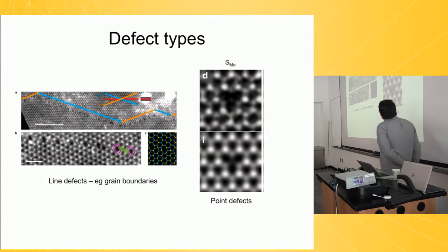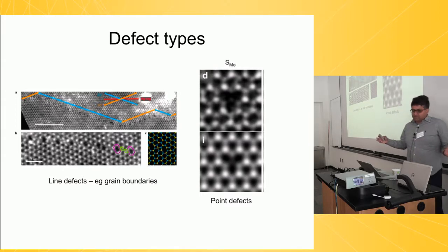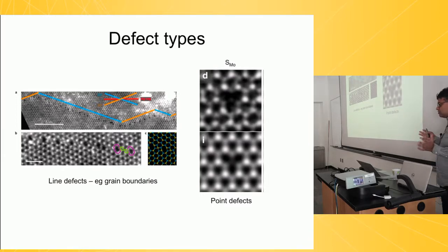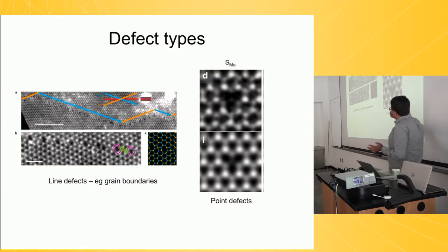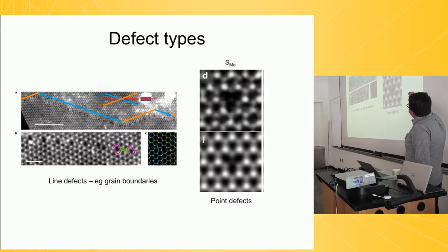Good. Now, in terms of defects that you can have in these materials, since you have a two-dimensional material, we can broadly classify defects into two types. Defects can either be a one-dimensional defect. So shown here is a grain boundary. What you can see are defects in the atomic positions. And these form a one-dimensional line, and these grain boundaries can stitch together in many interesting ways. You can also have point defects. So shown here is one particular point defect where there's a hole in the material just at one single point. So point defects and grain boundaries.